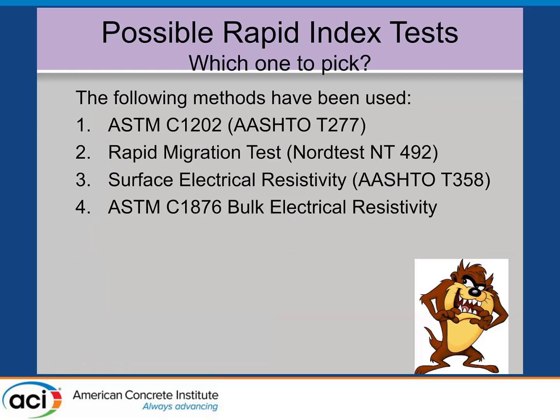And there's several. I'm going to talk about 4 of those methods: 1202, this Nord test method, rapid migration test, the surface resistivity that's been adopted by AASHTO, and the bulk resistivity adopted by ASTM. But even so, which one you pick? You're not going to specify all 4. You've got to pick one. You can't have competing limits with different test methods, or you'd have a real dog's breakfast.